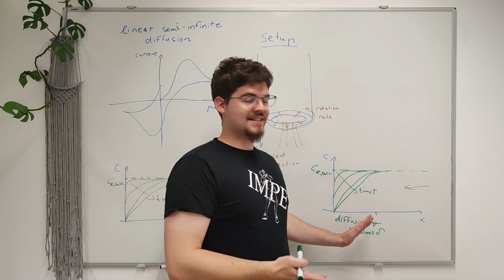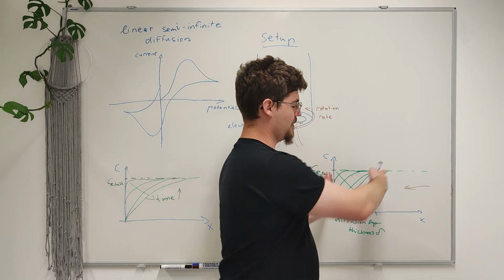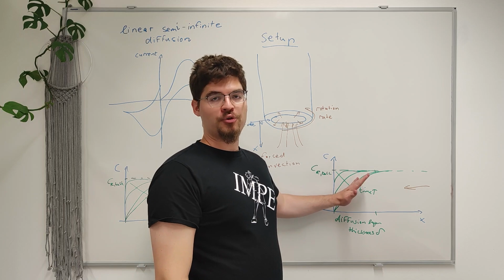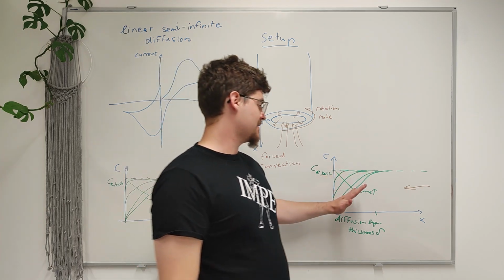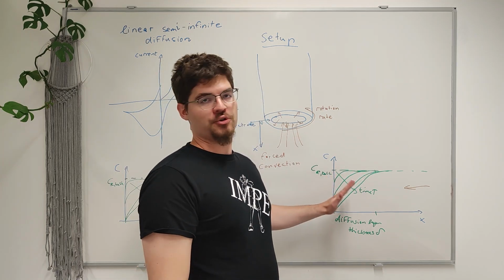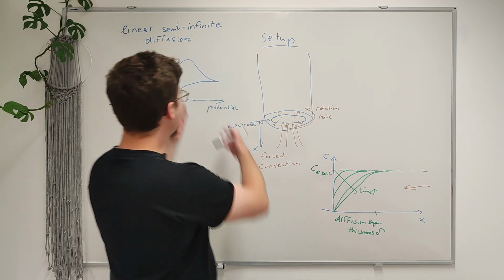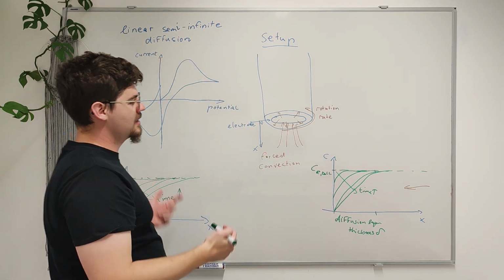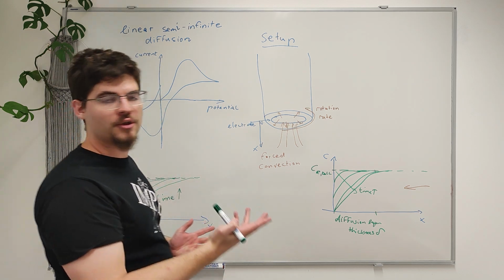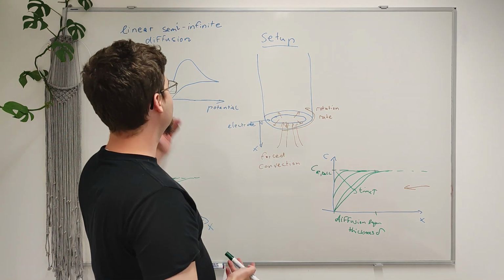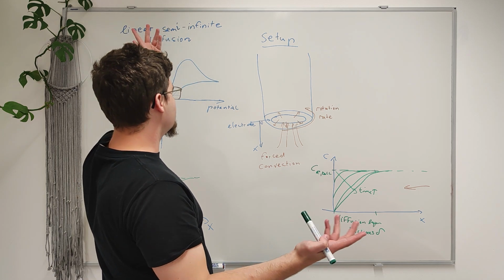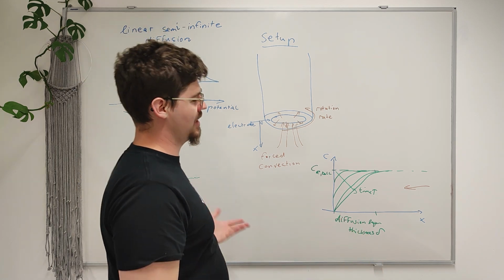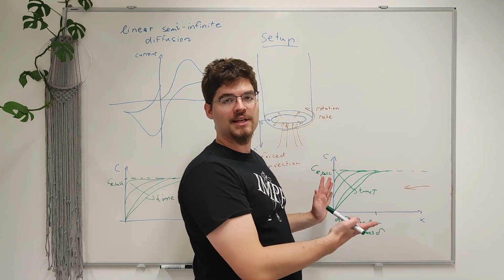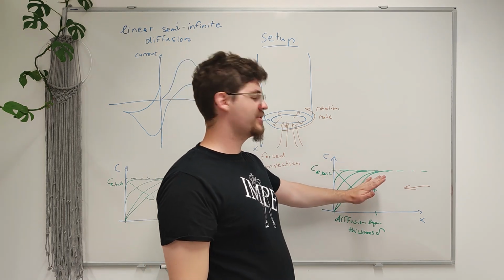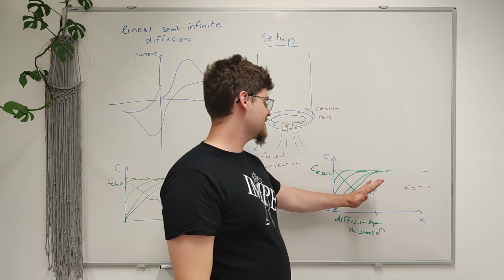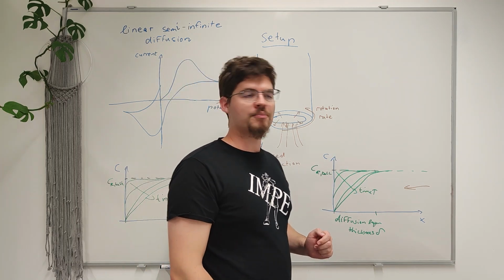Now, because this thickness is constrained and can grow no further, the concentration gradient, which determines the flux due to diffusion, is also constrained. Before, we had a peak, because the concentration profile extended further and further, the gradient decreased, and so the diffusion limited current decreased as well. Now we have a constrained diffusion layer thickness, and therefore also a constant current. So this means we run into a current plateau and not a peak.